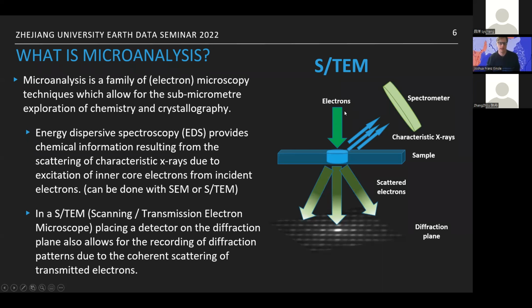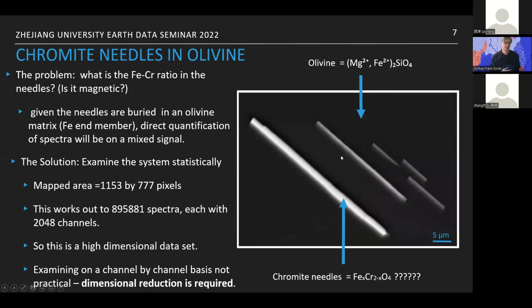So I have a way within a STEM instrument to look at both chemistry and crystallography. And we're going to use this to our advantage to understanding some very early complex materials. So one way to understand this and what I'm doing here is we're going to look at these iron chromite needles found in the olivine grains from the Admire pallasite. The question that I was presented with by my collaborator Claire Nichols in this case was, are these needles magnetic? And whether or not they're magnetic comes down to what is the ratio of iron to chromium.